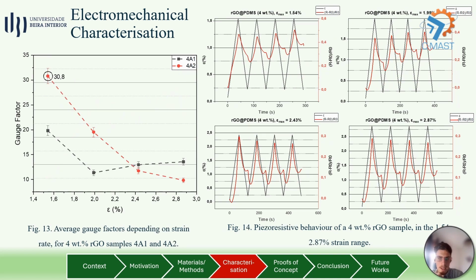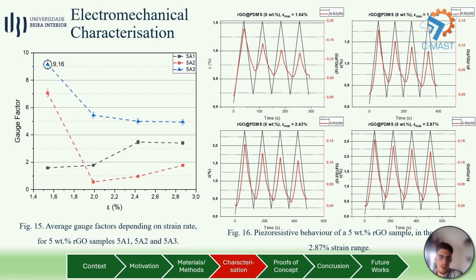4% samples had the highest sensitivity, reaching a maximum average gauge factor of 30.8, an indicator that this may be the concentration within the percolation threshold. Its piezoresistive behavior, however, despite linear with the mechanical strain, the rising peaks denoted the difficulties in returning to the initial state, either due to the viscoelasticity of the material, the hysteresis effect, or a conduction network that may react differently depending on the strain rate.